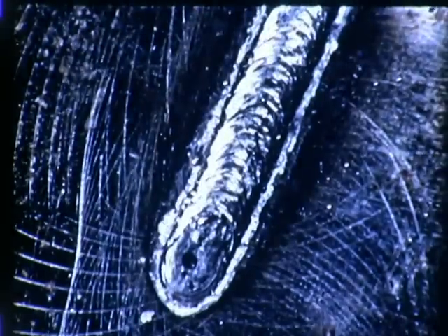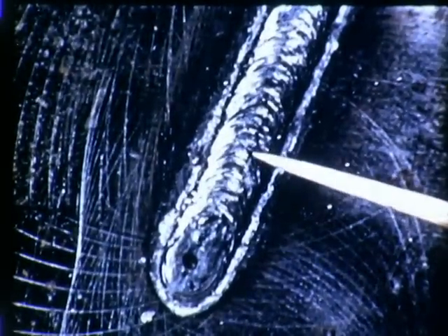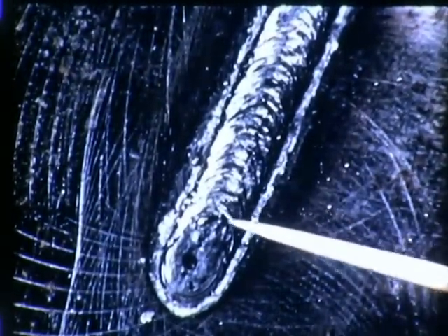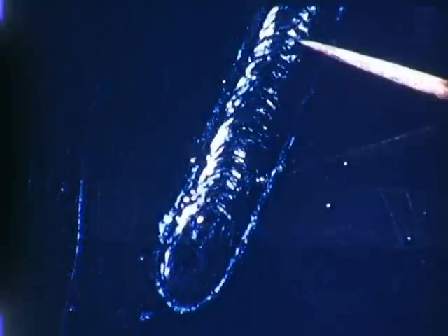If your weld is good, the ripples will be uniform and will build up a smooth bead. This cross-section cut shows that a good bead will join the plate with no overlap or undercut. It will have complete fusion and good penetration. This is good welding. Now, let's look at some of the common errors.